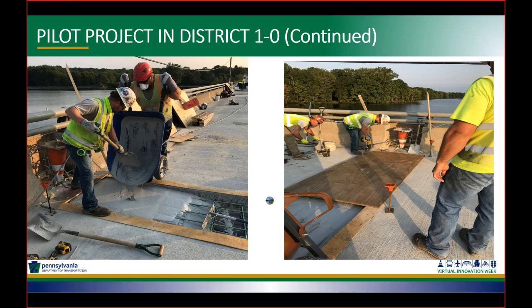The other interesting thing about the link slab is you want to finish the UHPC slightly higher than the adjoining deck. So if you look in the photos, you'll see a strip of plywood. It's about a 1/4 inch thick plywood immediately adjacent to the joint. And then the form is actually placed on top of that. What we're trying to do there is to finish the UHPC slightly higher than the existing bridge decks. And then what we do is we come in and actually grind off the top 1/4 inch of that UHPC so that it's flush with the adjoining deck.